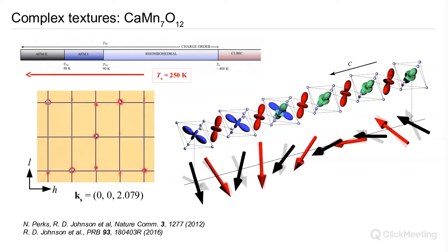And this incommensurate structural modulation can be understood in terms of an incommensurate variation in the occupation of, for example, a 3d x² minus r² and a 3d y² minus r² orbital, which I've shown in kind of cartoon form in this 1D chain, going from blue to green to blue, interleaved by a square planar coordinated manganese 3+ at the A site. And then at low temperature, this is accompanied by a helical magnetic structure. And this helical magnetic structure, again, is quite unusual. It doesn't have a continuous pitch.